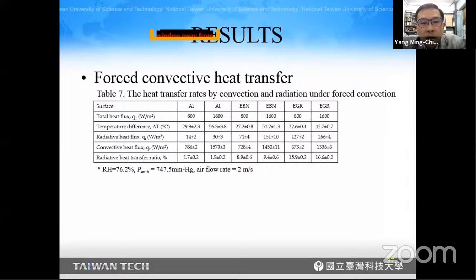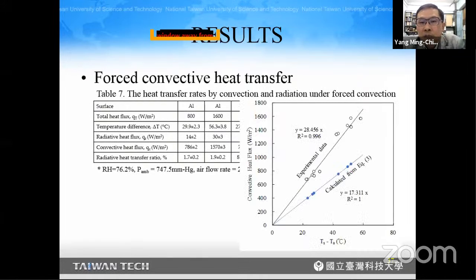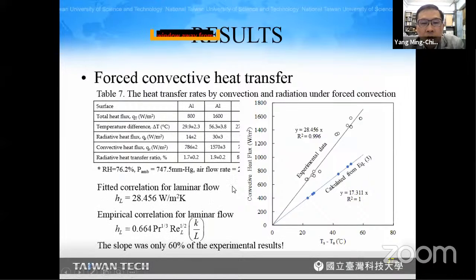So the coating did take a non-negligible part of the heat transfer. And we can plot this convective heat flux against the temperature difference and obtain a very good fitted linear regression result. This shows that the correlation for laminar flow provides a heat transfer coefficient of 28 watts per meter square per Kelvin. And in the textbook, we can find a very frequently used correlation given here.